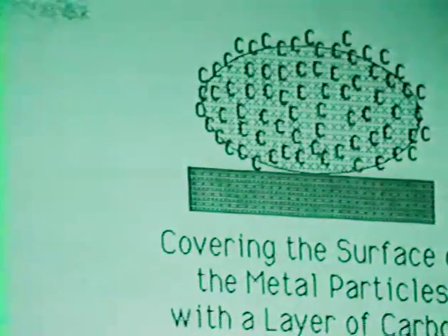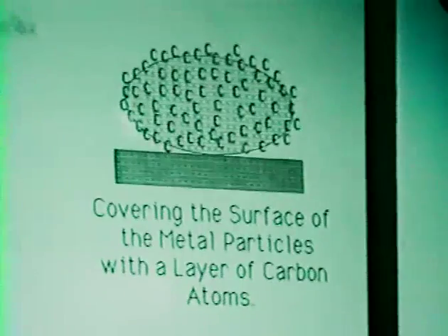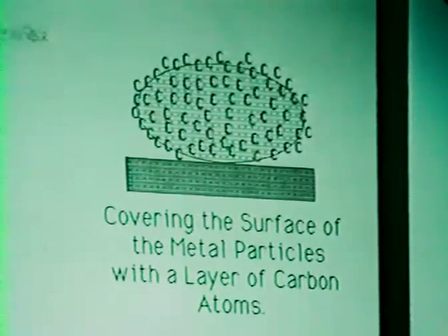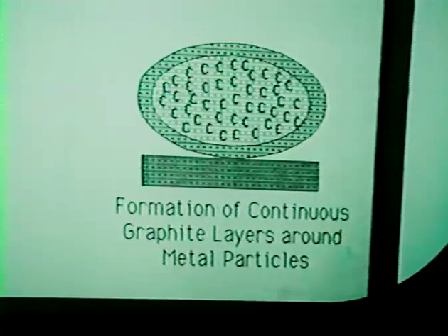Now, subsequently, you are having filled the sink, and then you get kind of an overflow, and finally you get a graphite layer. And it's not just an artist impression, but I remind you of the former figure. We have seen these graphite layers just surrounding the particle. So what happens now, if thermodynamics are trying to get their way, and if there is a segregation of carbon, well, you get a huge mechanical strength on the particle. And that I find is very important.